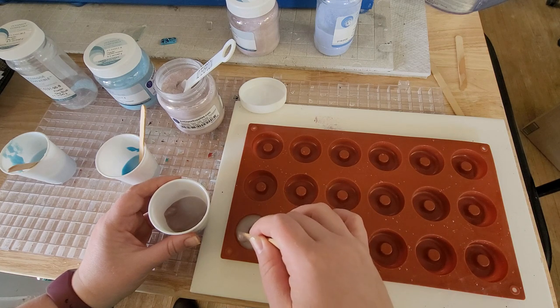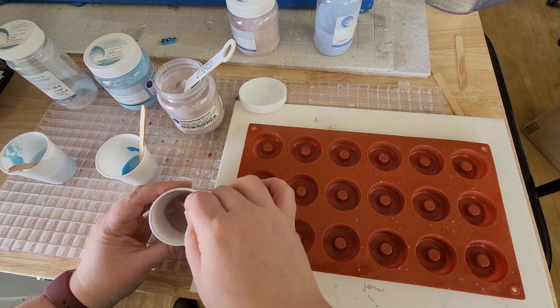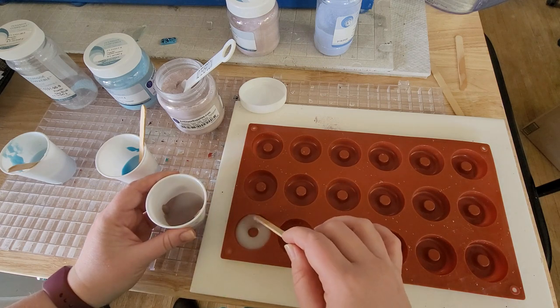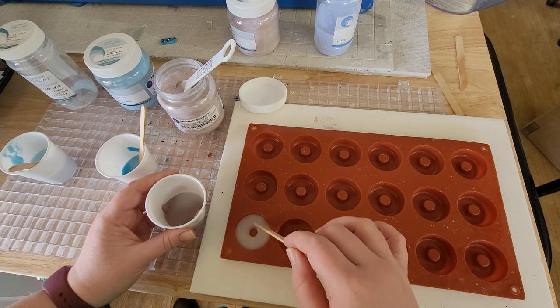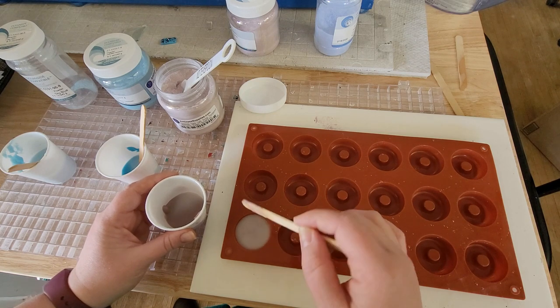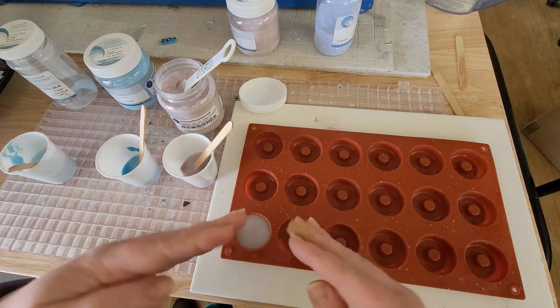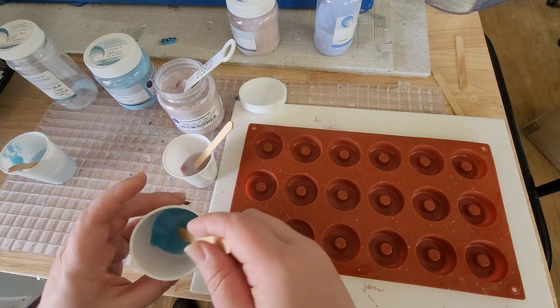And so I want to try to displace as much of the water as I can with glass, that way when it freezes, I just want enough water to bind everything. I don't want there to be too much water that whenever it dries, we get a lot of cracking. I'm suspicious that that's what's going on.